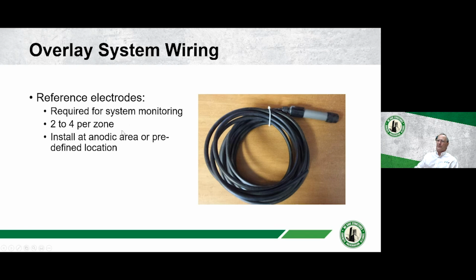The preferred way of installing reference electrodes is to do a half cell potential survey, identify the areas that are most anodic or the ones that have the most corrosion activity, place your reference electrodes there, and once you turn those most active areas cathodic, you have achieved your objective for the system. The other way is to put them in predefined locations so that they're easily identified and located for future access.